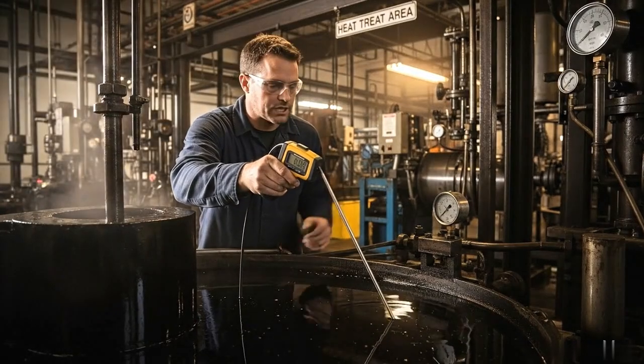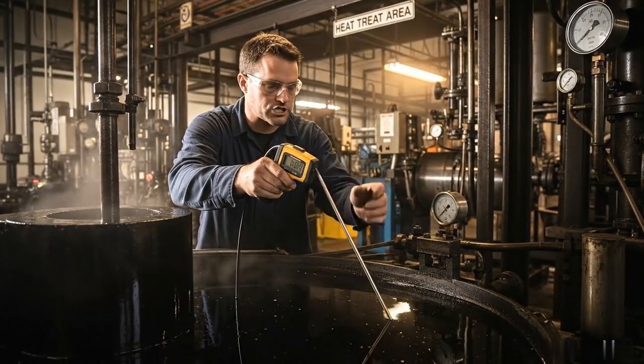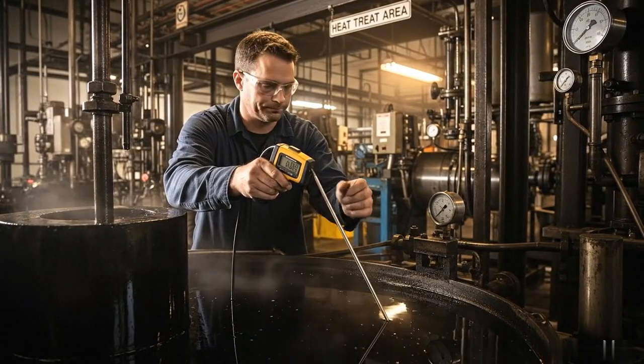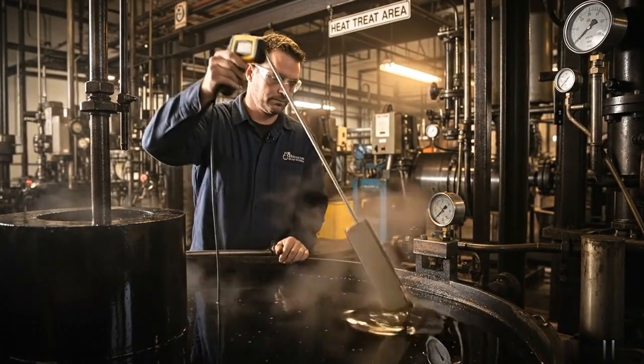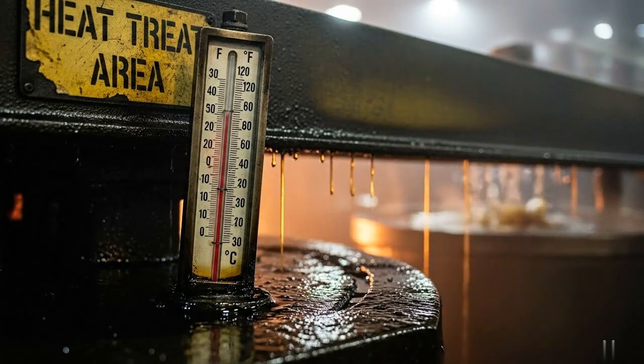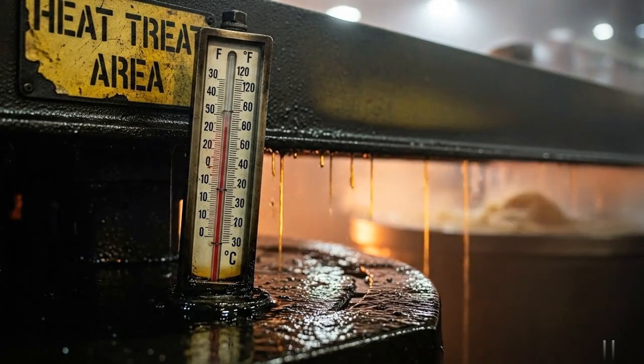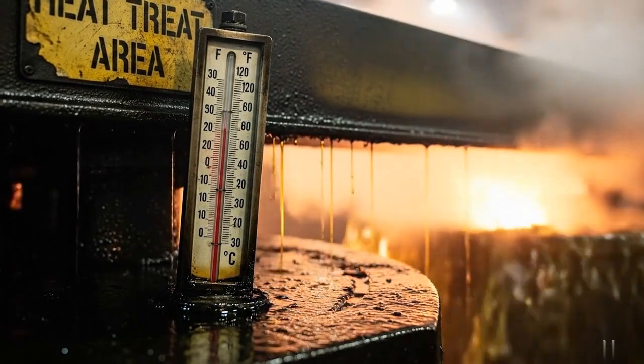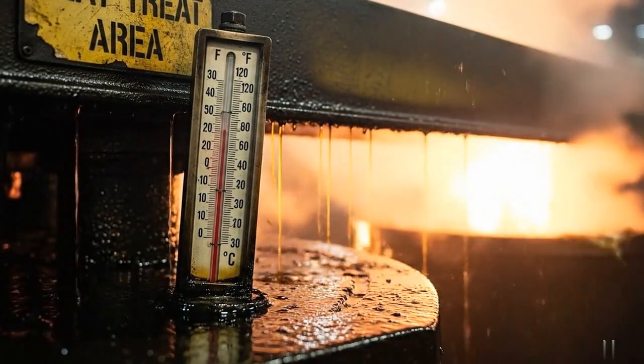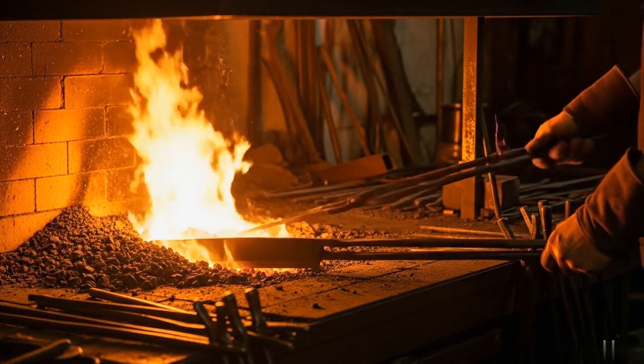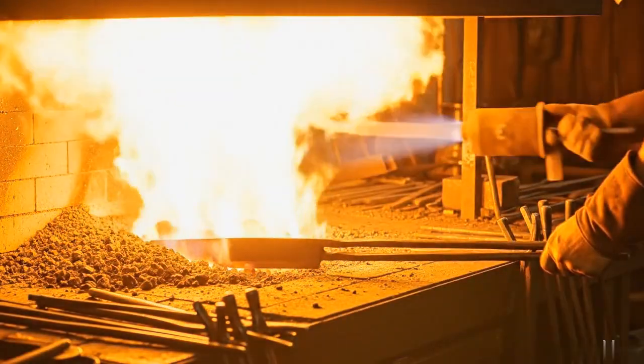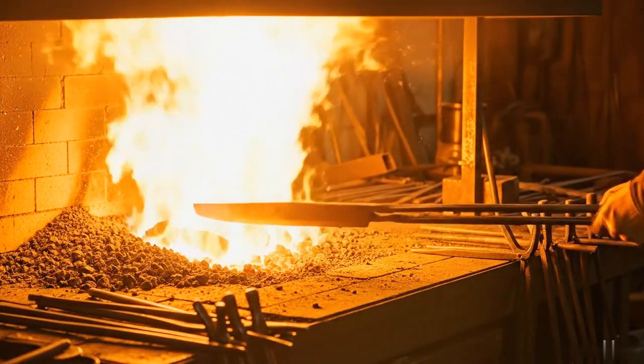After normalization, it is time for the quench, so I check my vertical tank of oil. The oil is preheated to about 120 degrees to lessen the violent shock to the steel. The forge goes to full blast and the blade goes in for the most critical heating event.